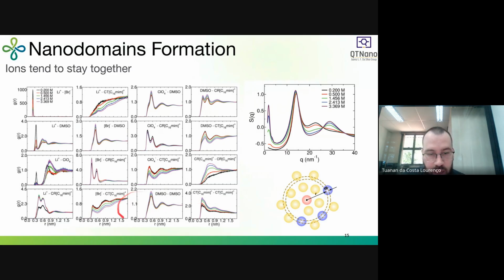So looking to the RDF, we can say how the interactions within the species in the electrolyte are, how strong those interactions are, and also how many ions or molecules I have around each ion and each molecule. So if you go here to the left side, we can see the interaction of lithium and DMSO. When we have here in black the lowest concentration of ionic liquid, we can see this high peak here and a low peak in the second solvation shell. That means that the major part of the interactions between lithium and DMSO are in the first solvation shell. So we have close contact here.